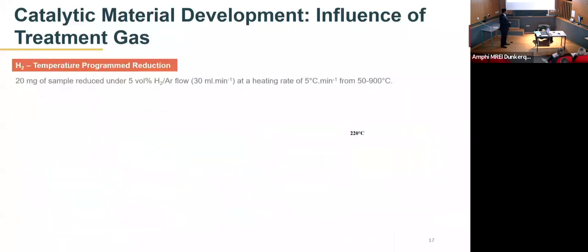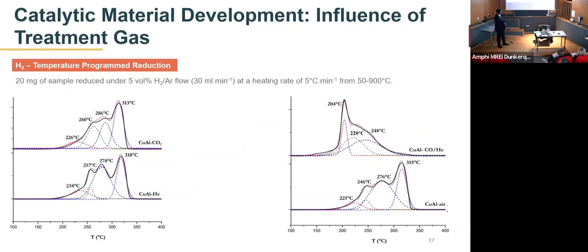And the next material characterization technique that we used for our sample comparison was the hydrogen temperature programmed reduction. In this case, we passed hydrogen gas through 20 milligrams of our sample, and we see the different hydrogen reduction peaks that we get. So these are the hydrogen reduction peaks. So the first